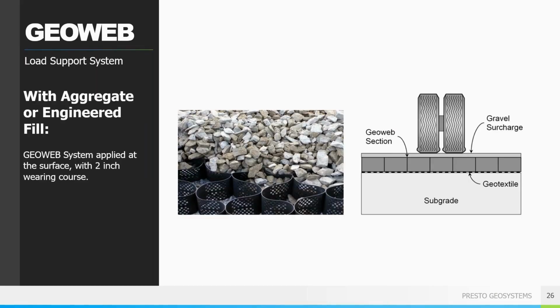So a typical GeoWeb section is going to have a geotextile below the cells, and this geotextile can be anything from a 6-ounce non-woven up to an enhanced woven, depending on your subgrade strength and maximum loads. Then your GeoWeb is typically filled with your granular material, and we do recommend a 2-inch wearing surface over the top of the cells.